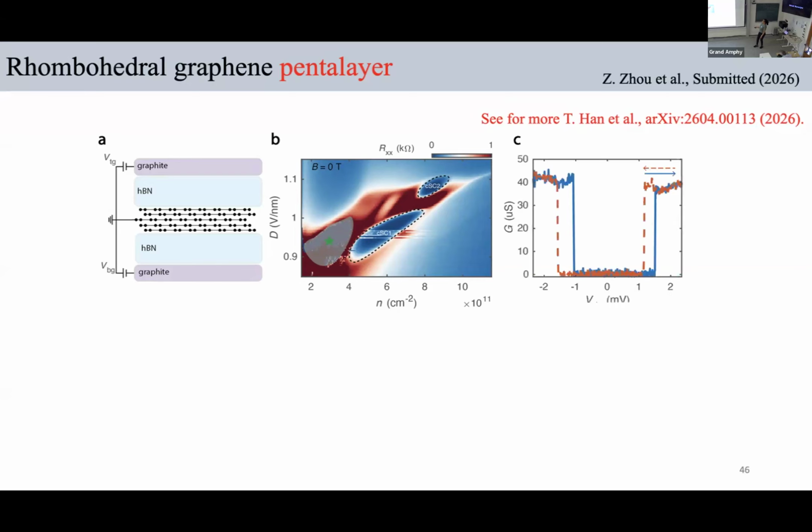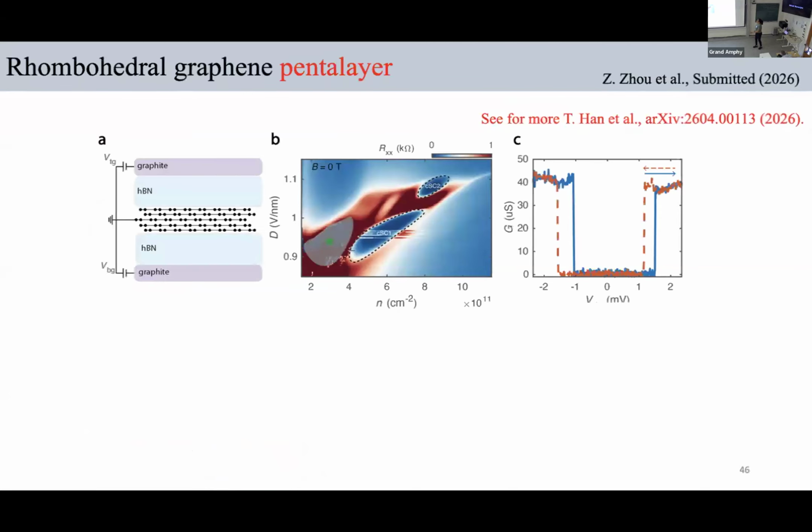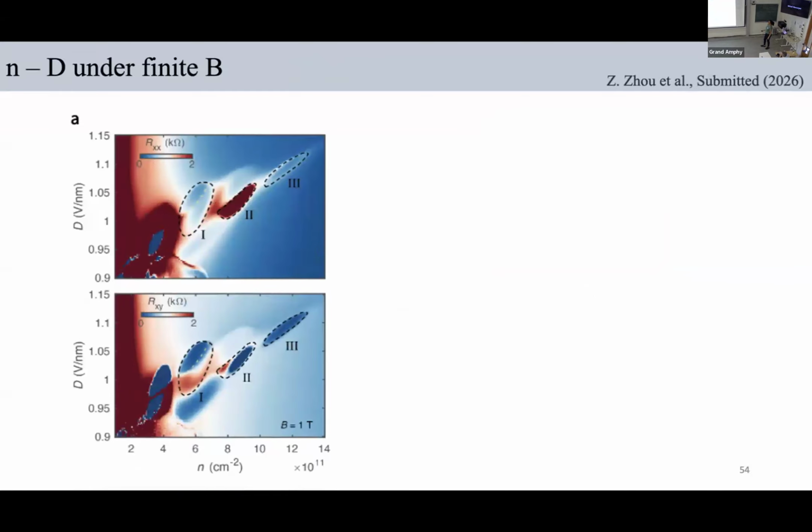So chiral superconductor, I'm not spending too much time. All I want to say is that indeed this insulating state has bias dependence. I'm sure there are many theorists here and they will like to hear something that is Wigner crystal. I think I kept that slide because I thought I would not bore you. But basically this state is a Wigner crystalline state, okay? But what we are interested in is this: the moment we increase the magnetic field, here the superconductivity goes down, but here a superconducting pocket comes up and here a superconducting pocket comes up. So let me just show you that. Okay, so region 1 is here a superconductor, here what it is I will show you, and here also a superconductor I will show you.